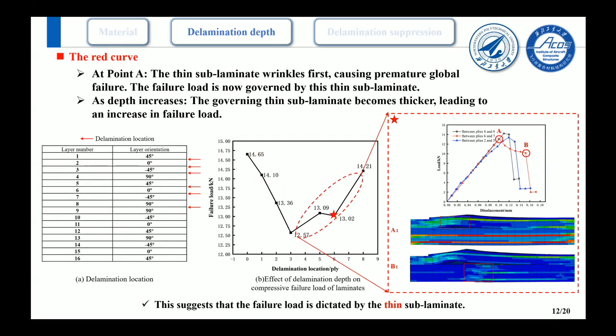Now please observe the red curve, which represents the deeper delamination. At point A, the thin sublaminate wrinkles first, causing premature global failure. The failure load is now governed by this thin sublaminate. As depth increases, the governing thin sublaminate becomes thicker, leading to an increase in failure load.